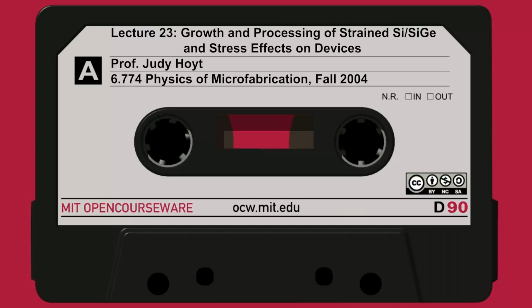And this is a good paper, Derek Houghton's paper from 1991, who describes the kinetic model and explains the fact that there's no one critical thickness at a given germanium fraction. What he plotted here was a summary of the critical thickness above which dislocations form as a function of germanium fraction of the silicon germanium layer for different growth temperatures. So if you're growing at 900 degrees, you're very hot, and it's very easy to nucleate dislocations, and they travel very rapidly. You tend to then get the equilibrium critical thickness, that's this line here.